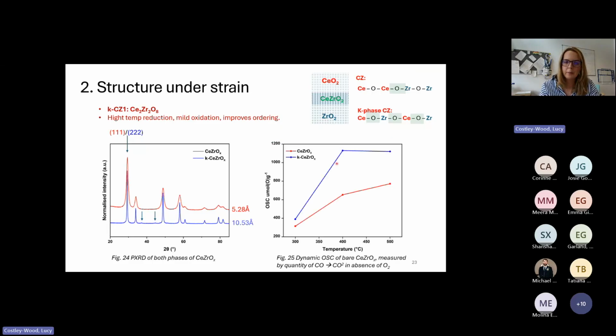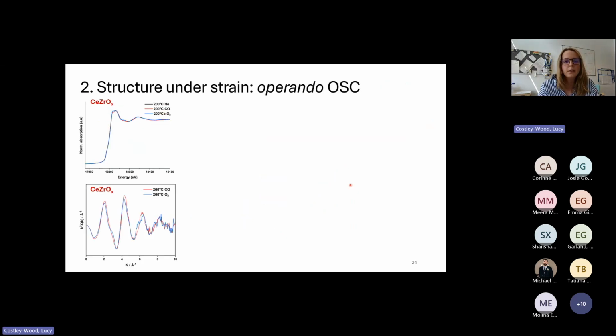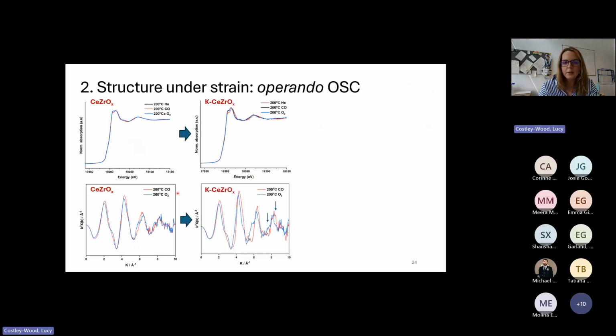So comparing here the kappa phase in blue with the material that we were looking at just a minute ago in red. You might be wondering then why this isn't the commercial material for three-way catalysts, and it's because you significantly lower the surface area by doing this treatment, and the material is unstable above 800 degrees. So just to show you then, these were the figures I just showed with the original ceria zirconia material, and these are the changes instead that we see with our kappa phase, and particularly in k-CeZrO4 here, you can see a really significant cubic to tetragonal transition.